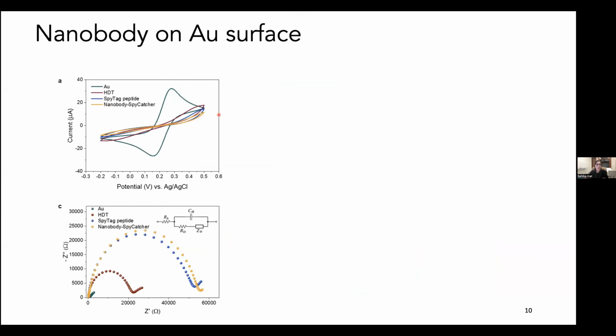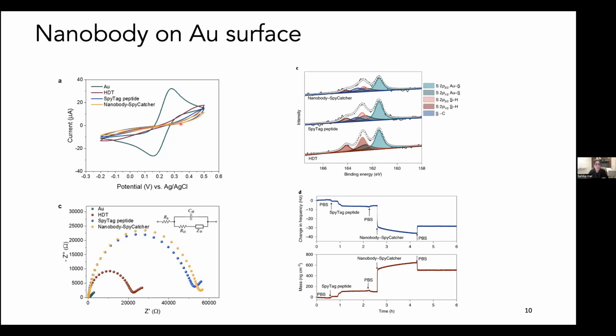And we do get to these numbers and characterize the field characterization techniques to understand how much of these nanobodies we have on the gold electrode surface and whether these multi-level functionalization is working properly, by using typical techniques such as cyclic voltammetry and impedance spectroscopy. Both of them are showing us that as we anchor the nanobody, the final layer is always giving us higher impedance and lower current from the gold because the nanobody is covering the surface properly.